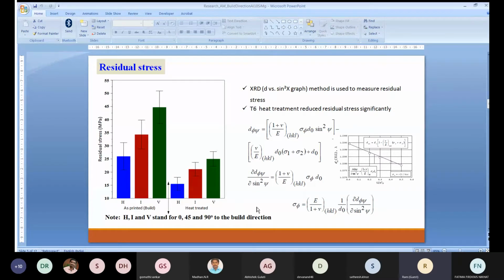first what we do, we use the powder and get the d-spacing in the stress-free state. Okay, and we put the samples and tilt the samples to several angles and capture the d-spacing value and plot the d-spacing value with respect to the square of the sine of the tilt angle. Okay, then if you take the slope of the curve, it will give you the residual stresses.